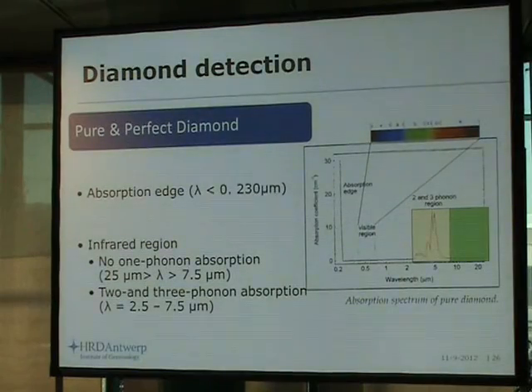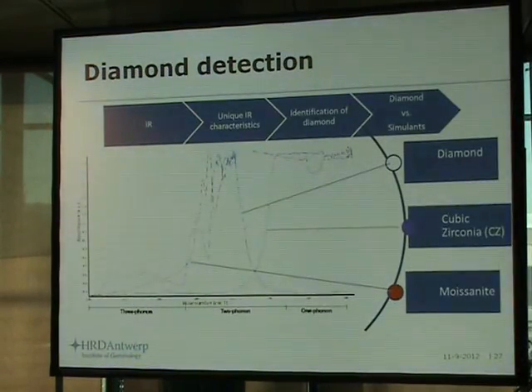And why is this now important or interesting for us? If you put in typical imitations, such as a cubic zirconia or a moissanite, then you see that the curves that you acquire or you measure are completely different. So it's a very unique spectrum which allows you to identify a diamond. So that's the first plus, I would say, to identify it clearly, diamond or not a diamond.